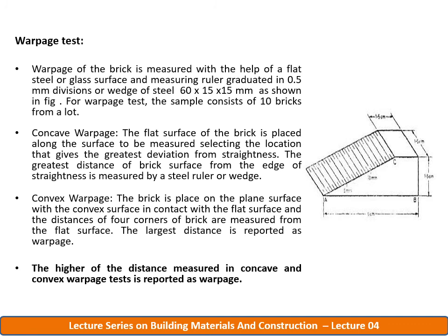In case of convex warpage, the brick is placed on the plane surface with the convex surface in contact with the flat surface, and the distances of the four corners of the brick are measured from the flat surface. The largest distance is taken as warpage. The higher of the distances measured in concave and convex test is reported as warpage.